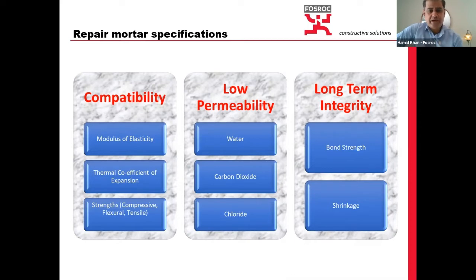So when we say compatibility, that means compatibility in terms of modulus of elasticity, thermal coefficient of expansion, and strengths. So most of the times we start from the strength and we end up here. So strength should not be the only criteria to select or specify a repair mortar. We should also look at these factors for the compatibility.